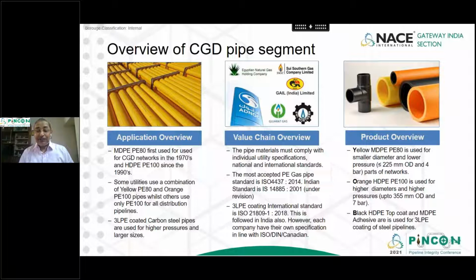However, each Indian oil and gas company has its own specification, and they have taken elements from ISO, DIN, and Canadian standards. In the product overview, yellow MDPE PE80 is used for smaller diameter and lower pressure, say up to 225 mm OD and 4 bar pressure. Orange HDPE PE100 is used for larger diameters and higher pressures, up to 355 mm and 7 bar pressure. And black HDPE top coat as well as MDPE adhesive are used as part of the 3LPE coating of steel pipelines.